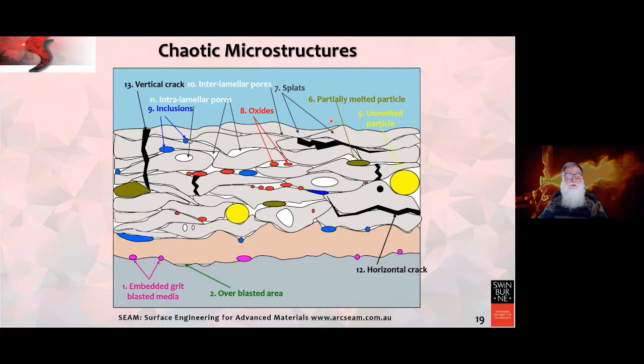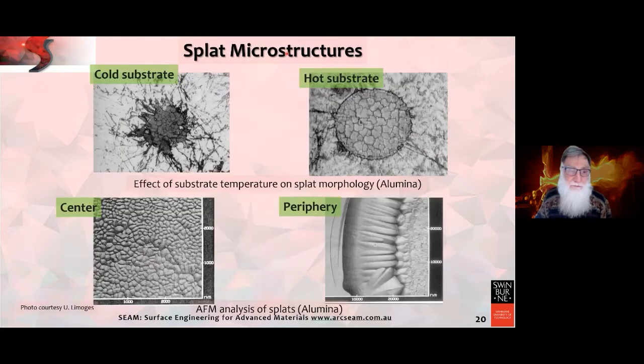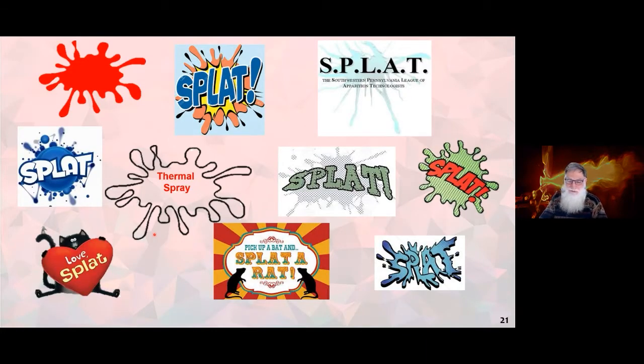There we go. So there's a complete picture of the taxonomy of these chaotic microstructures, or ugly microstructures, or strange materials, or, and I'm going to keep on saying, beautiful. Beauty is in the eye of the beholder. So these all begin with splat microstructures. We're looking face down now, directly onto the material that you're coating. We could see a cold substrate or a hot substrate. We either get the fragmentation or flower pattern shape, or we get these nice saucer shapes of cracks. If we look at cross sections, we're able to see columnar growth, or very, very small grains. Splat is how we define all of these materials, and it's the combination of many of these splats, layer upon layer upon layer, which give rise to these beautiful coatings.